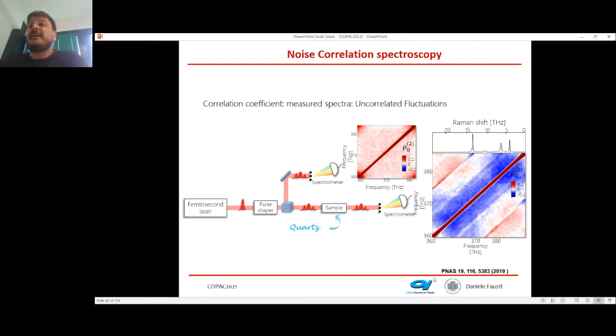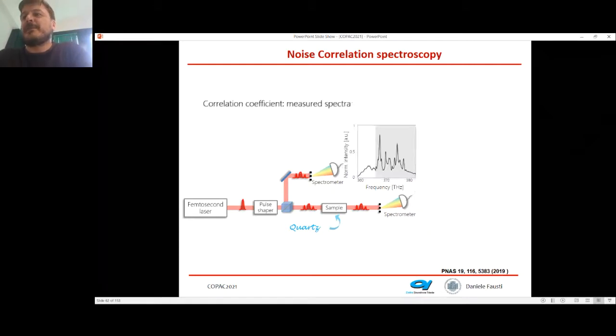And this is actually a very interesting spectroscopy, because you can have a Raman response which is measured on a time scale as short as your light pulse, but with a frequency resolution which is just determined by how large your frequency correlation is. And you can do more. This is a bit of detail, but I can actually imprint the fluctuations only on one part of the spectrum and leave the other part with coherent fluctuations.